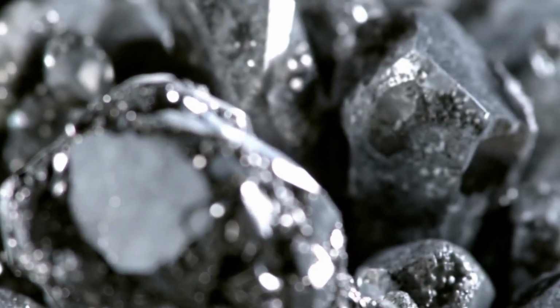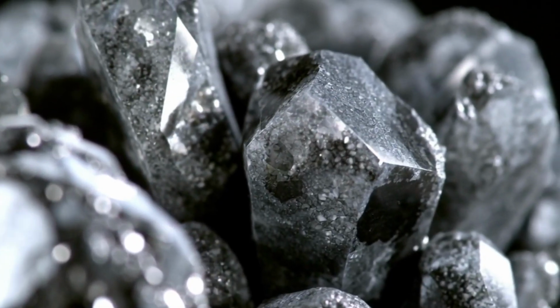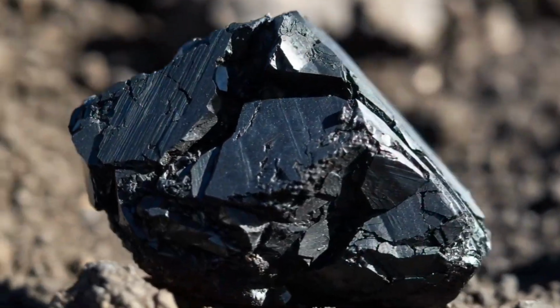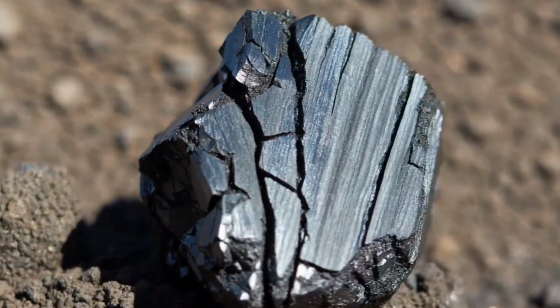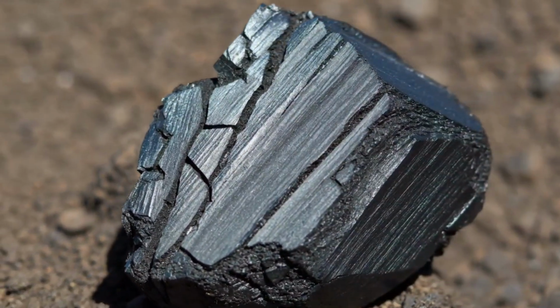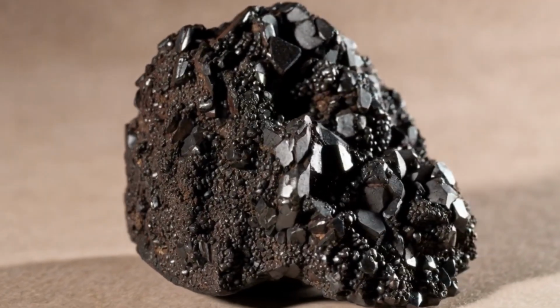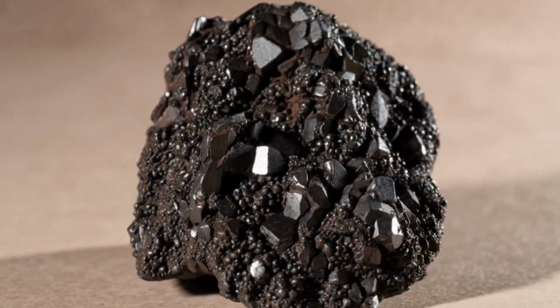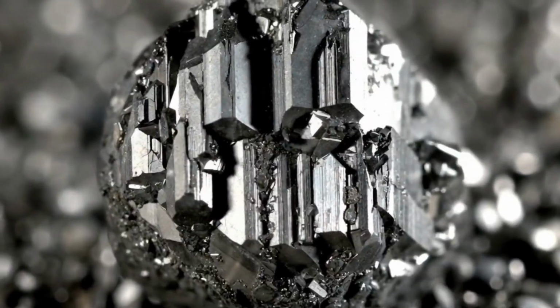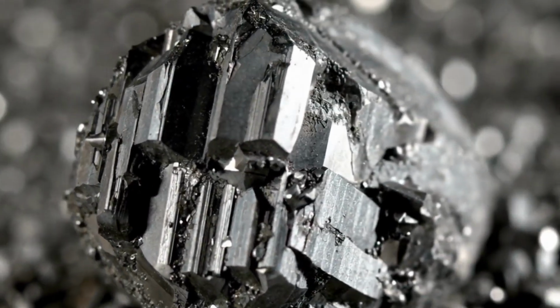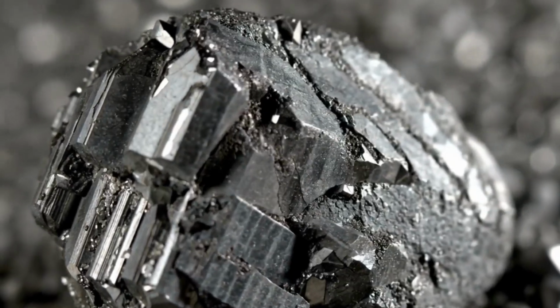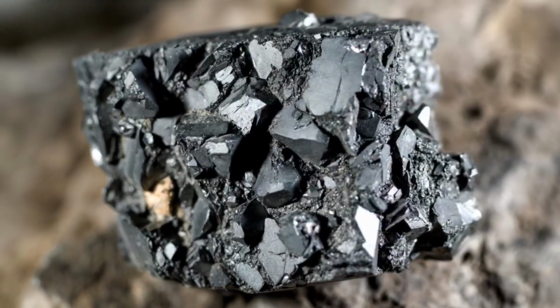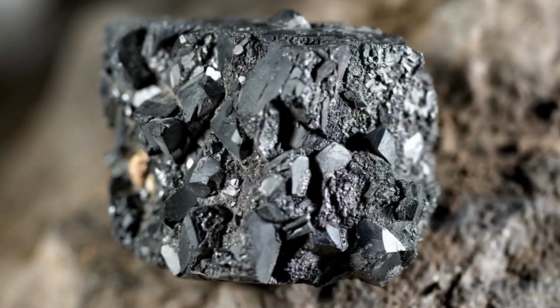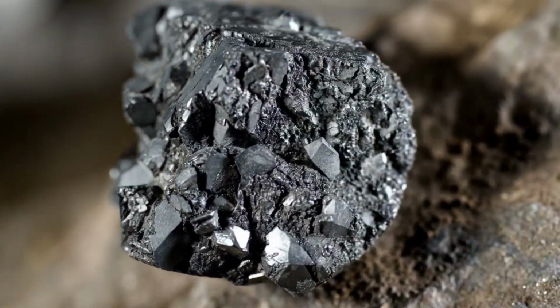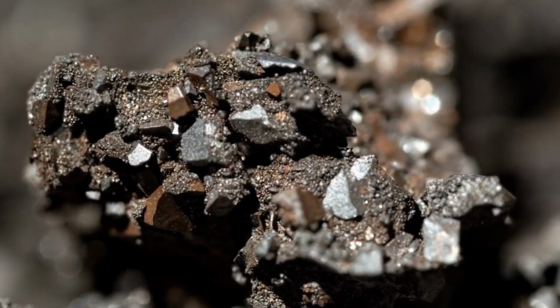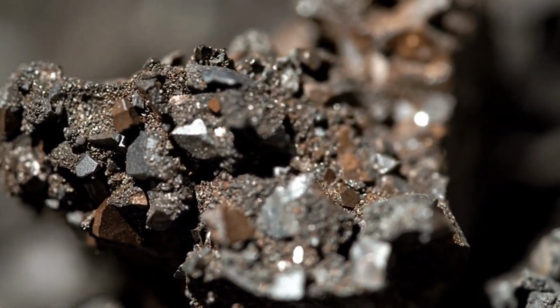Chromite ore is mixed with a carbonaceous material, coke or anthracite, fluxes are added, and the mixture is melted at temperatures above 1500 degrees Celsius. The carbon removes oxygen from the chromium, reducing it to metal. The resulting molten ferrochrome, after solidification, is crushed and sent to steel mills. It is an energy-intensive process. Producing 1 ton of ferrochrome requires 3 to 4 megawatt hours of electricity. This is why the largest ferrochrome plants are built in areas with low electricity costs: Kazakhstan, South Africa, and India.